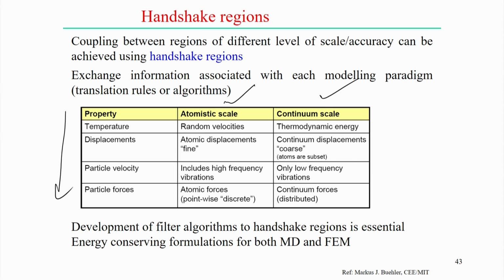Particle velocity at the atomistic scale includes high frequency vibrations, but at the continuum scale only low frequency vibration is relevant. Particle forces at the atomistic scale are represented by atomic forces, which are pointwise and discrete. But at the continuum scale the forces are represented as continuum forces, which are distributed. So there is a huge difference in representing these properties at the different scales. Therefore, it is essential to develop a filter algorithm in the handshake region, and also energy conserving formulas at the handshake regions for both molecular dynamics and the finite element method when you try to link between these two scales.